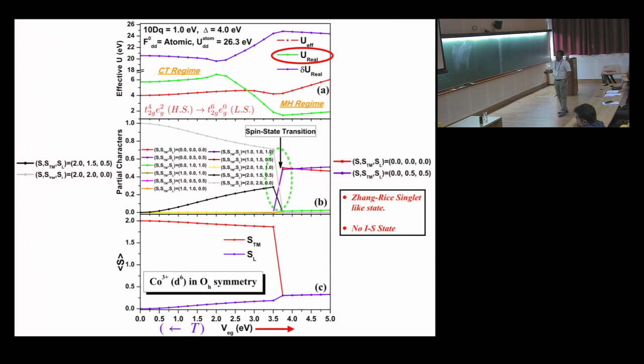And however, for the people who are experts, we don't find the intermediate spin state that was proposed at some point. And you will see when this transition takes place, the value of the spin here is something like 0.25, okay? For both these, and these 0.25 actually form a very correlated singlet state, giving you the net singlet. Okay, so what we see here is along with the spin state transition, which changes relative occupancy of T2G and EG levels, you have this large change in U that is observed in experiments, also going through this crossover from one kind of insulating state to another.